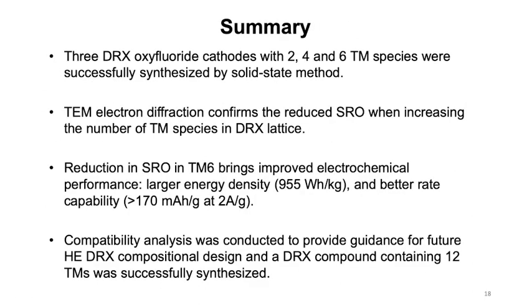To summarize our key findings in this work, first, we designed and synthesized 3 prototype DRX oxyfluoride cathodes with different numbers of transition metal species: TM2, TM4, and TM6. We further used TEM electron diffraction to confirm that when you have more transition metal species, you will have less short-range order. And the reduction in short-range order as a consequence leads to improved electrochemical performance from TM2 to TM6. And specifically for TM6, it achieves a high energy density larger than 950 watt-hours per kilogram, and also excellent rate capability, which demonstrates larger than 170 milliampere hours per gram when cycling at a high rate of 2 ampere per gram.